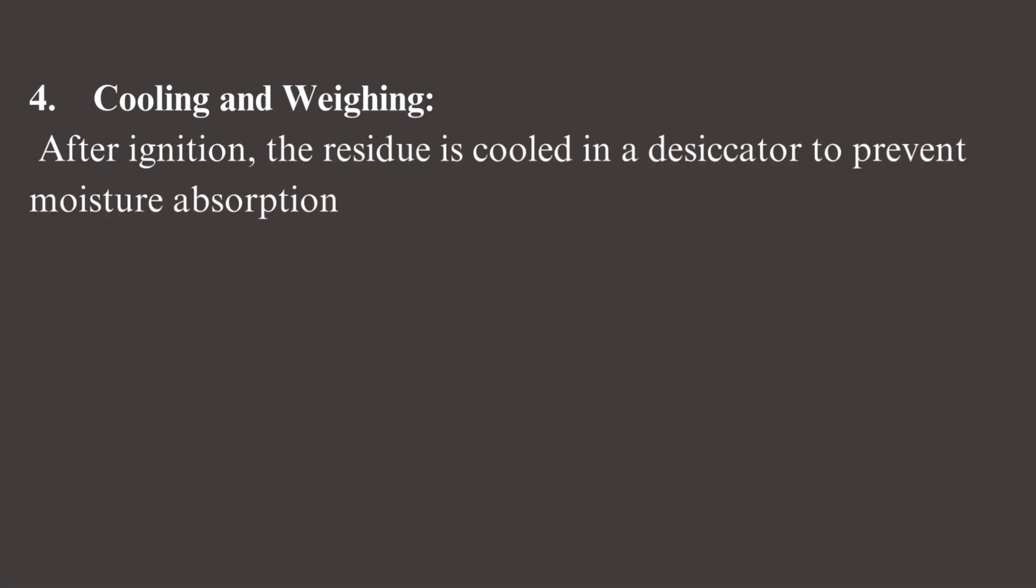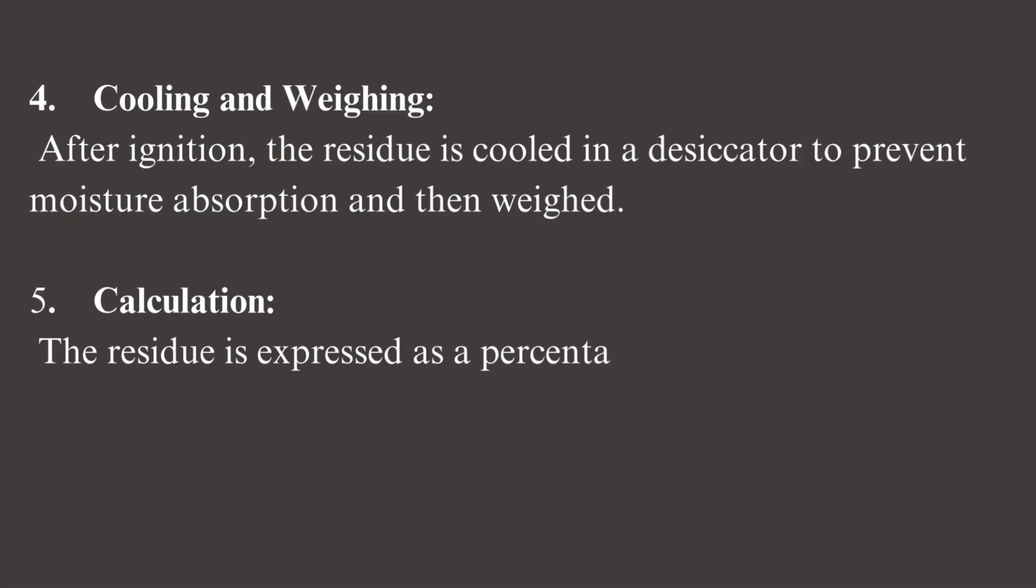Cooling and weighing: after ignition, the residue is cooled in a desiccator to prevent moisture absorption and then weighed. Calculation: the residue is expressed as a percentage of the original sample weight.